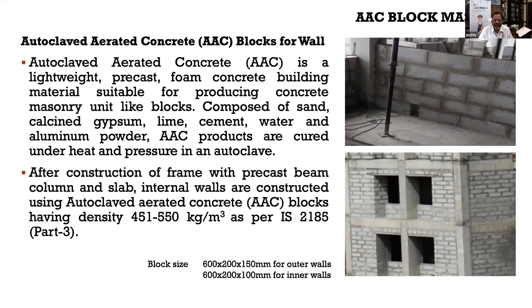So AAC blocks have direct advantage over burnt clay brick. AAC blocks are a lightweight concrete, and they are made with lightweight precast foam concrete. And the composition, if you see of AAC block, it uses gypsum, sand, lime, cement, water, and aluminium powder. This aluminium powder reacts with cement to create foam, and it becomes a lightweight concrete. And if you compare the density of AAC blocks to the brick, brick density is 1900 kg per meter cube, and here the density is 450 to 500.